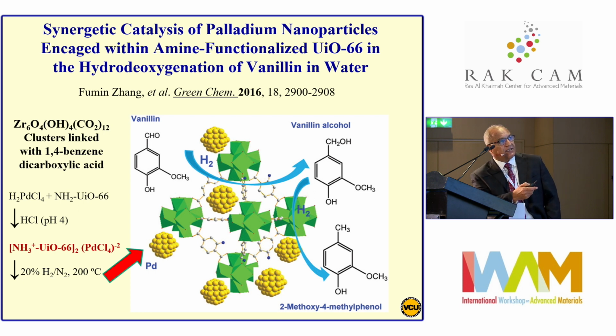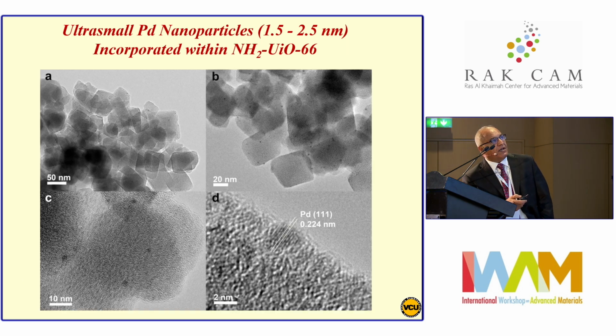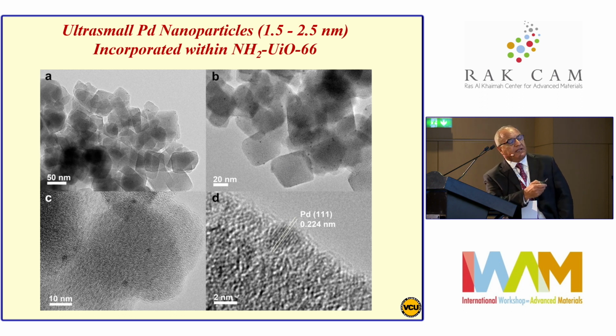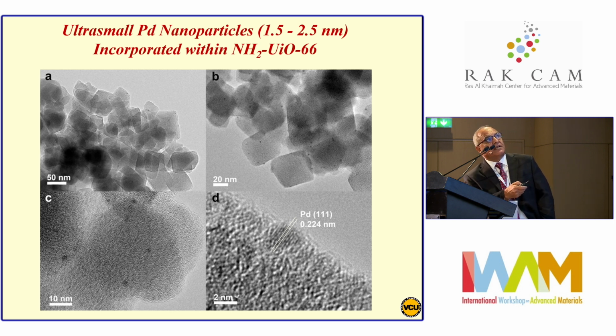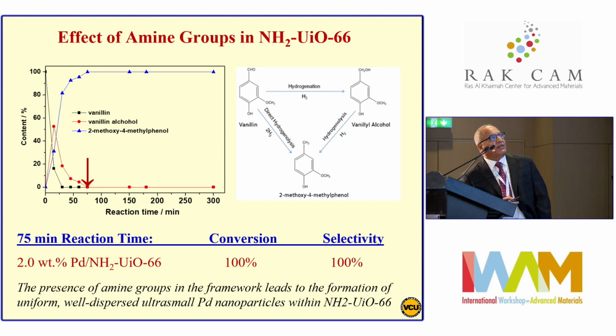And actually, this is what we see. We see very small particles that can be formed in this case, and only when we use the amine UiO66, that the palladium particles are between 1.5 to 2.5 nanometer, which is very small for such a reaction, and they are definitely incorporated, most of them, within the crystals of the UiO66. That's very much reflected in the reaction steps.